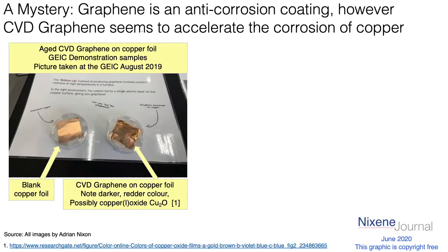So this is a picture I took last year in August, and you can see here there are two petri dishes, each with a copper foil sample in. These are probably about 7 centimeters by 7 centimeters, to give you an idea of the scale. They're on the demonstration table at the GEIC, and this one on the left is blank copper foil with no graphene on it. But you can see this one with graphene on it is a slightly different color. It's a mystery why that color change has happened.